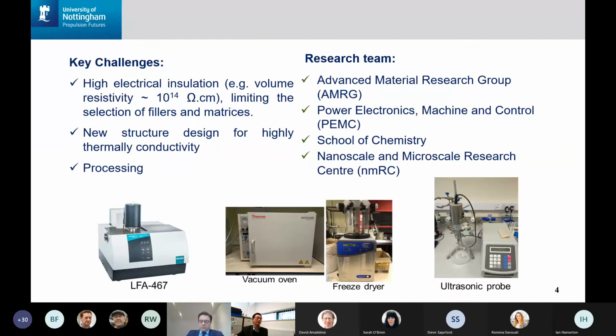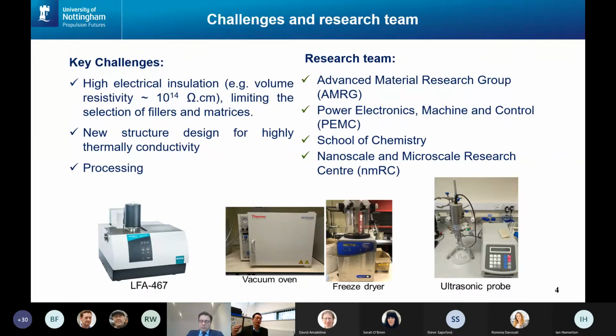So the key challenge, as I mentioned just now, is not only the high thermal conductivity, but also the high electrical insulation. Normally, for this kind of application, we really need the volume resistivity to be around or even higher than 10 to the power 14 ohm centimeter. Because of this requirement, it's really limiting our selection of fillers and matrix and also the selection of the process.